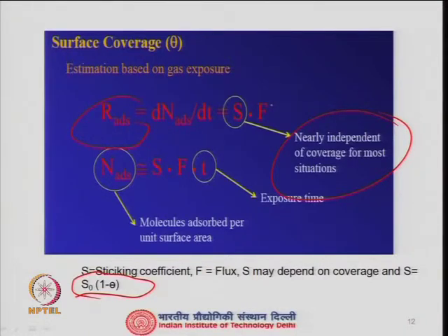If you just integrate this equation, it is S into F into t. I was talking about the exposure time earlier, and that is also important. It means your adsorption, or chemisorption, will depend on the flow rate of that gas, the number of molecules which are coming onto the surface, and for how much time. Time of exposure is also equally important.